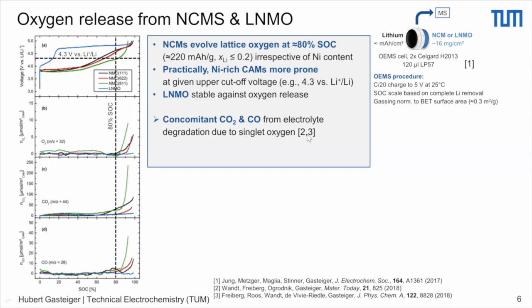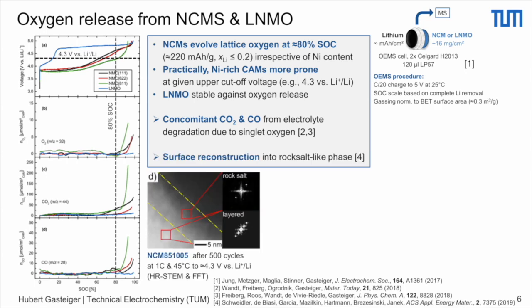And as I said, in our studies, we ascribe it to the reaction of the released singlet oxygen with the electrolyte. But as I said, there are other hypotheses in the literature. Of course, upon oxygen release, you get a material which is poorer in oxygen than the layered structure. And what one finds for nickel-rich materials is that it reconstructs into a rock salt-like phase.